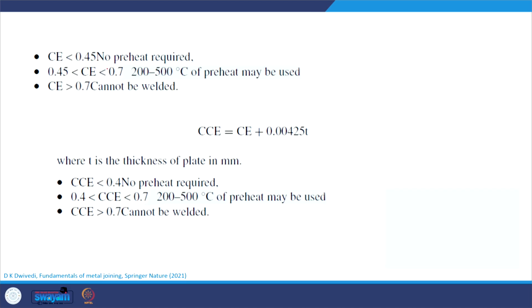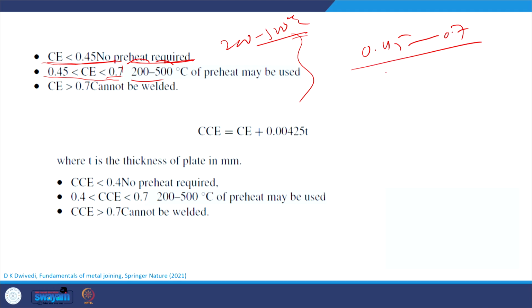So, if we see the typical thumb rules, if the carbon equivalent for a steel is less than 0.45, then we do not require much preheat, no preheat is required. If the carbon equivalent is in the range of 0.45 to 0.7, then the preheat requirement can be from 200 to 500 degrees centigrade. So, preheat range is 200 to 500 degrees centigrade depending upon the carbon equivalent.